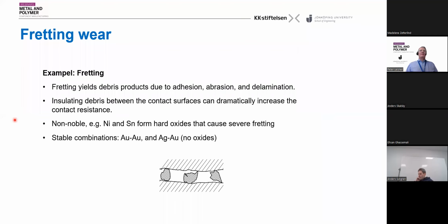And another example related to fretting is that you might have material which is loosened from the surface of the contact pair, which results in debris, which will lie in between the contacts. This itself will increase the electric resistance, but if it's, for example, particles from nickel or tin, it will form hard oxides, which will actually increase the wear of the two surfaces. Stable combinations are considered to be gold against gold and silver against gold. There you have precious metals that do not form oxides.